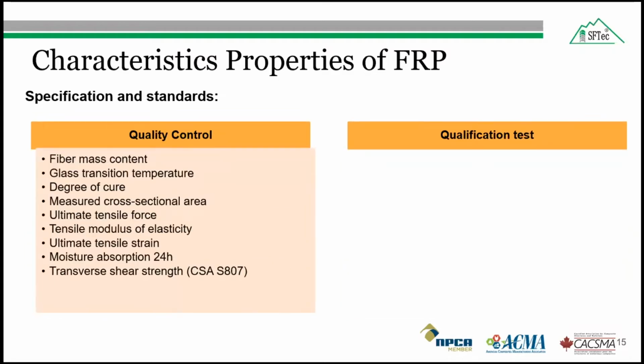This facility should be inside where the bar is manufactured. There they have to provide all these properties: fiber mass content, glass transition temperature, degree of cure, cross-sectional area, tensile properties, and CSA S807 requires an additional transverse shear strength.